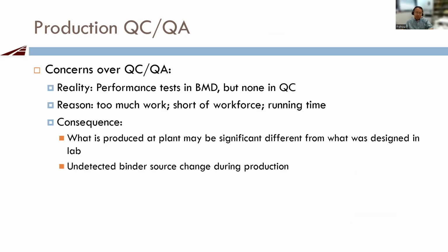But we do have some concerns. The reality is the performance tests are used in the balanced mix design, but none in the QC and the QA process most of the time. The reason is too much work, short of workforce, and too long running time. So what's the consequence? The consequence is what is produced at the end at the plant may be significantly different from what was designed in the lab. That's what we really don't want to see.